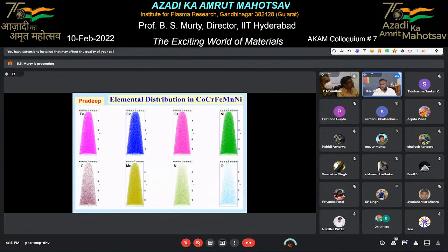And people have been using atom probes to see whether they are uniformly distributed or not. So here is an example. We made a 5-component alloy, put it into an atom probe. You can see every element is uniformly distributed. You can also see nitrogen, carbon, oxygen. You can even see hydrogen in a material, which has not been easy by any other spectroscopy technique. Atom probe can do that.